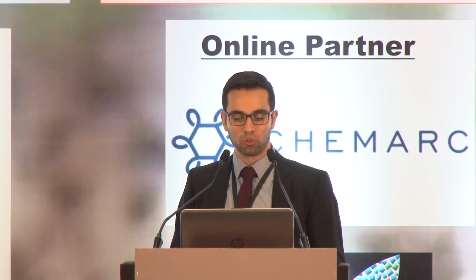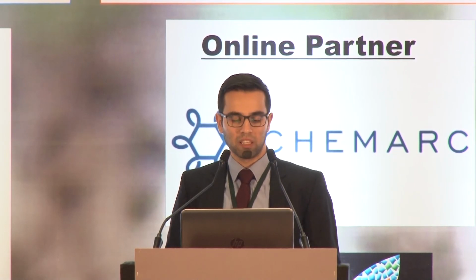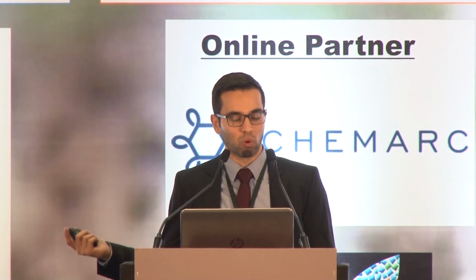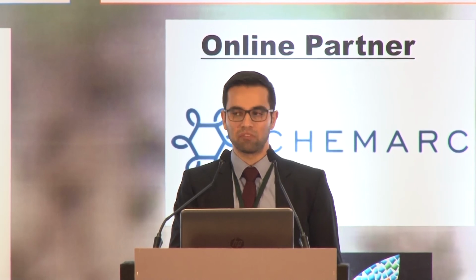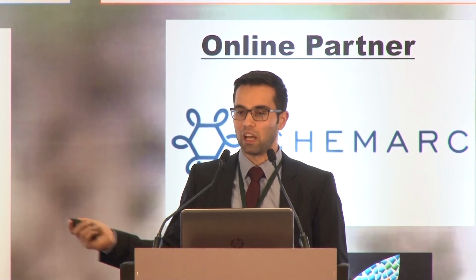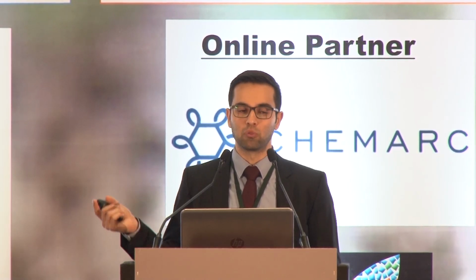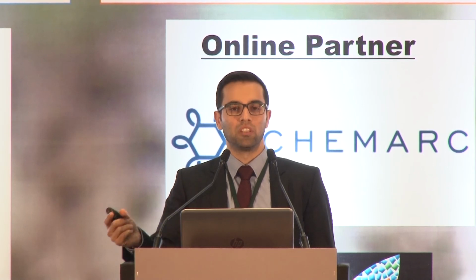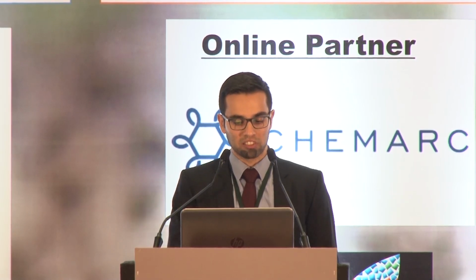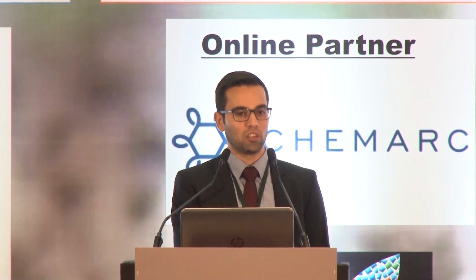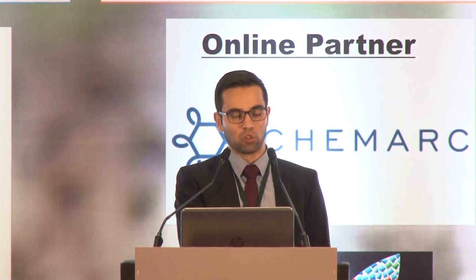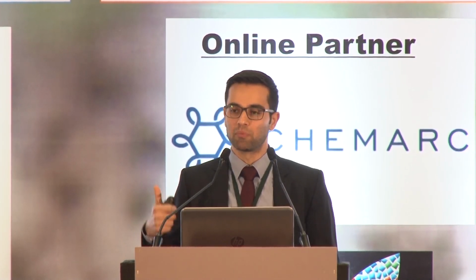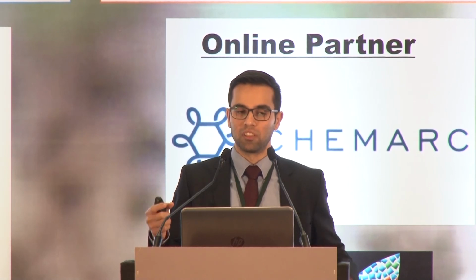The unfilled polymer we took here, Engage, an elastomer, will burn with 100% weight loss. And if you add 50, 75, 85 weight percentage, you will have improved thermal stability of up to 40 degrees Celsius. Now, to be fair, as scientists, that's not very fair because it's all related to the conditions of the measurement. So we did only 1 degree per minute. But this shows the trend.